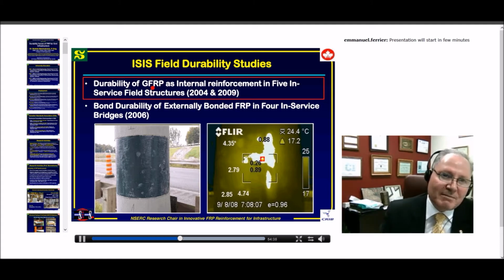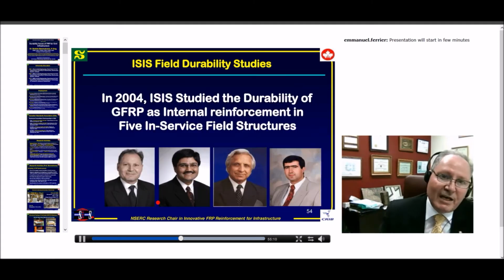I will be focusing mainly on the GFRP because, from the time when we did this study, it was shown clearly that the GFRP bars were behaving very well. At the time, in the Canadian Highway Bridge Code, we introduced GFRP as main reinforcement in bridge components, because before it was only secondary reinforcement. And this field study was extremely helpful to introduce GFRP as main reinforcement.